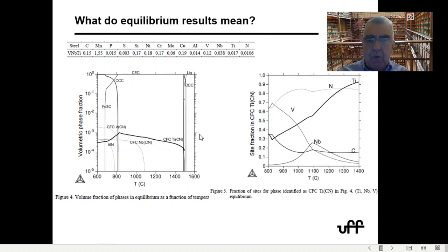Interestingly, when you look at the composition of this FCC phase here, you have a very strange variation. The titanium, for instance, is very high. About 90% of the metallic content in the carbonitride is titanium at the high temperatures. But when you come down in temperature, the titanium does not stay very high, and you have lower and lower titanium, and niobium and vanadium increase. Now, you probably think, well, this is very strange, because how is this titanium going to come out of the precipitate and the niobium is going to enter as it grows? Of course, this is what would happen if you equilibrate your steel at these temperatures, and not what will happen if you process this steel at a constant cooling speed, for instance.